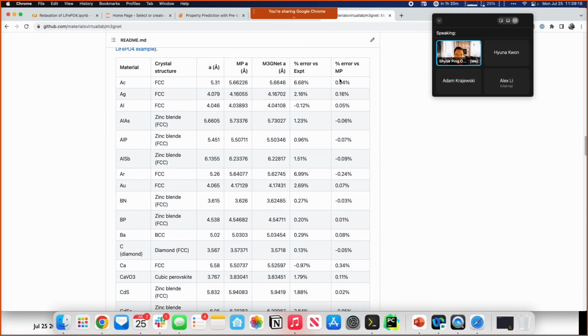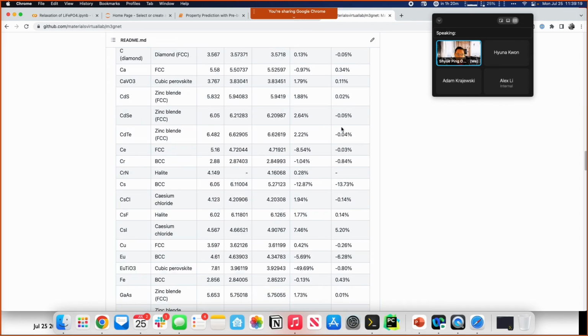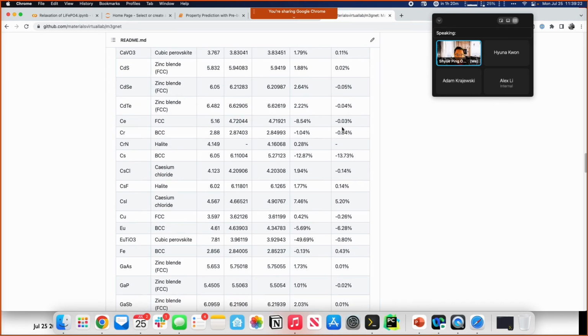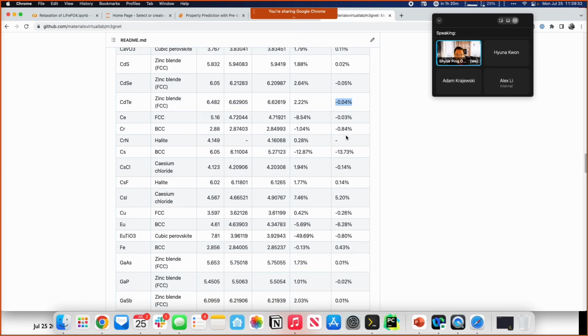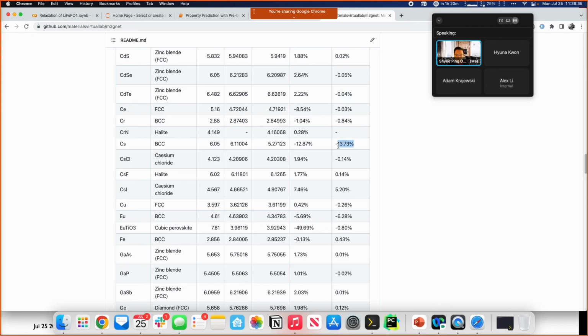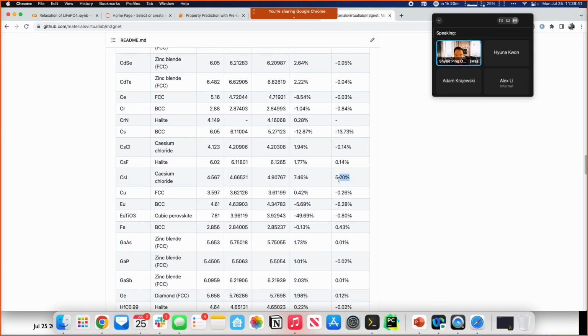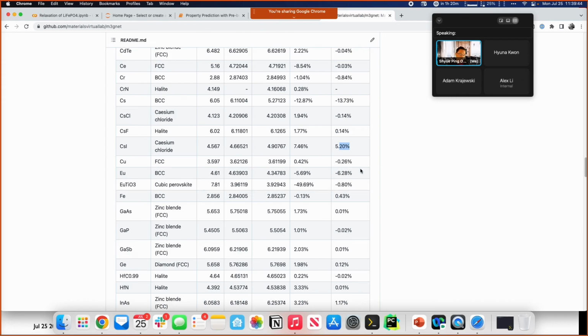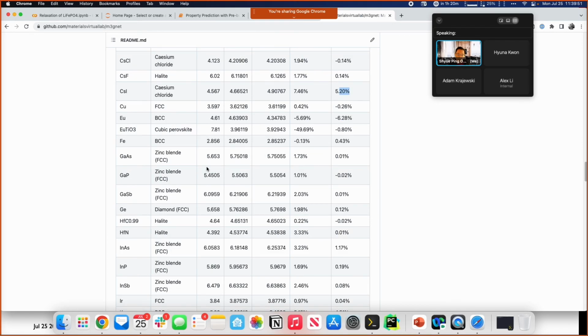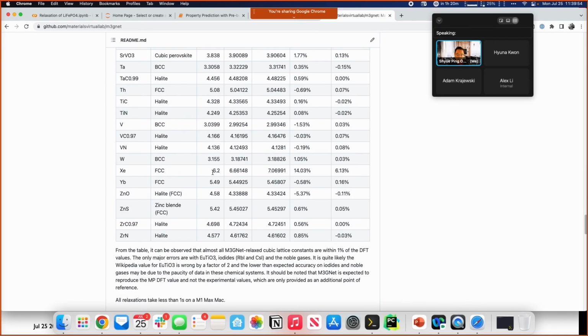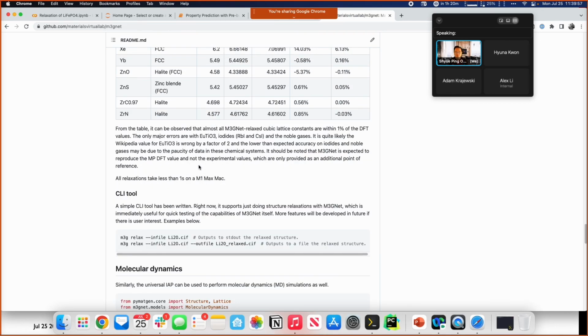And you can look at the percentage error with respect to the DFT lattice parameters over here. And what you will see is that for most of them, the errors are less than 1%, right? So in other words, we can get very, very accurate lattice parameters using these M3GNet potentials. There are a few errors that are slightly higher, for example for BCC cesium or cesium iodide, where the errors are somewhat bigger, and the reason is mainly because there's a lack of training data in the cesium system and the iodide systems, and that's probably the reason for these errors. Okay, but otherwise this is a proof of concept, right, that the universal potential that we have developed actually works quite well.